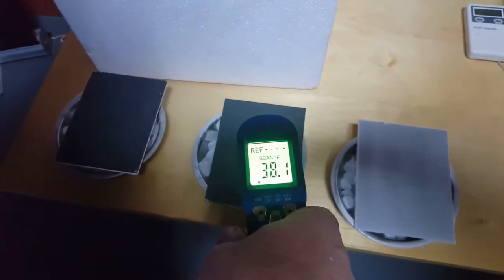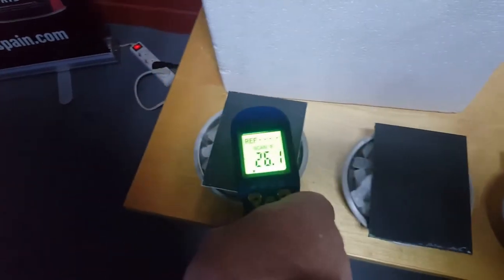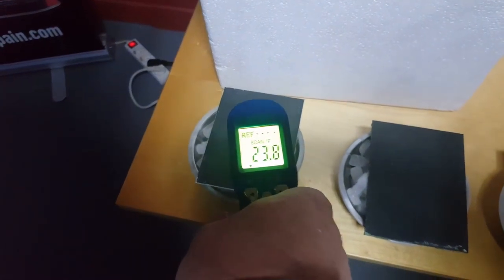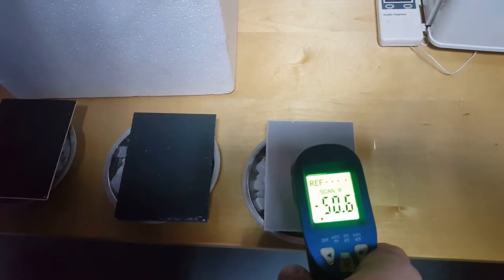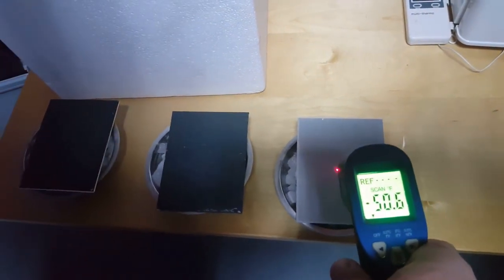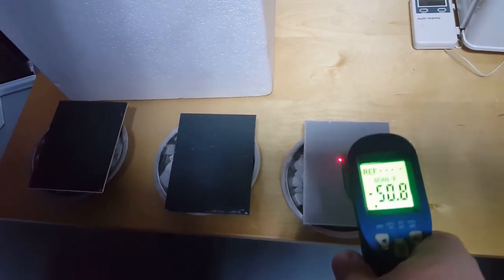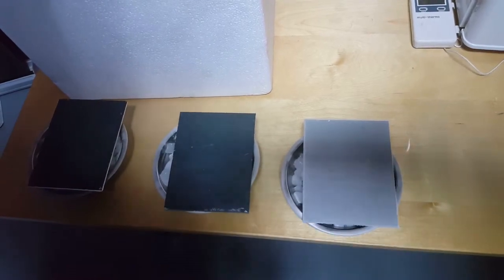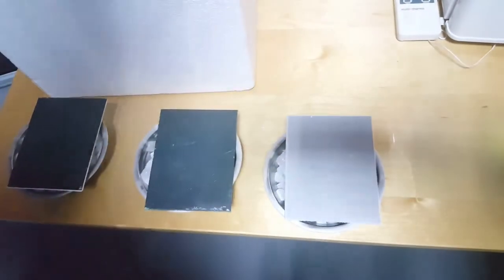Depending on the exact location that we measure on the uncoated sample, we may get temperatures warmer or cooler because of the contact with the dry ice. But the results from the coated samples are just incredible. Over 70-degree differential for the cork and over 60 for the ceramic coated. Those two coatings have literally stopped the transfer of cold into these metal samples.